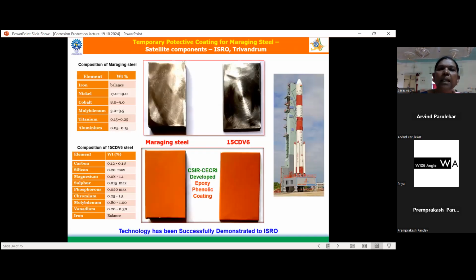This is another important technology we have developed for ISRO, Trivandrum. Normally they use coal tar epoxy for the temporary protection of high strength maraging steel for storage purposes, but coal tar epoxy is found to be highly carcinogenic, and it is banned internationally. They requested CECRI to develop an alternative to coal tar epoxy. We have developed an epoxy based phenolic coating for the protection of this maraging steel.